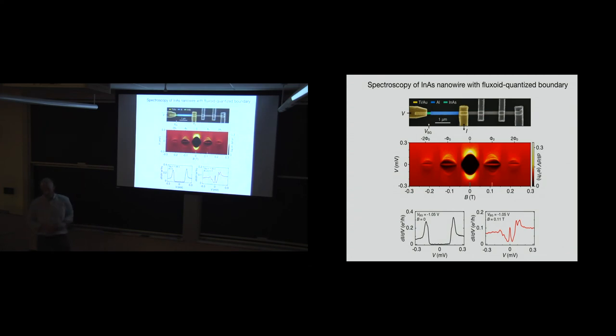But now let's look inside. So now I show you the other end of the wire, where the shell is on, and we do the tunneling spectroscopy, just like this Delft experiment. You try to inject a normal electron in. If you look in the zeroth lobe, where the phase is uniform all the way around the shell, you just get good old proximity effect, BCS superconductivity. There's the density of states at the black cut. You just get induced gap. Nothing can inject down below zero.